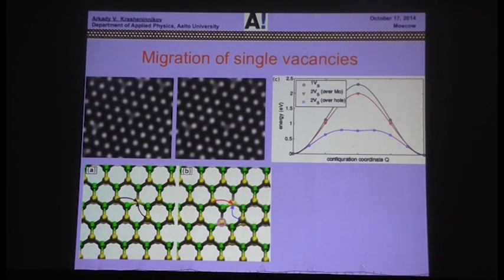To answer this question, we calculated the diffusion barriers for vacancies. Diffusion does happen. For example, the vacancy was here, now it moved to the next position, this way. But the barrier for diffusion is pretty high, about 2 eV, which means that at room temperature vacancies shouldn't move much, even accounting for electron beam effects.